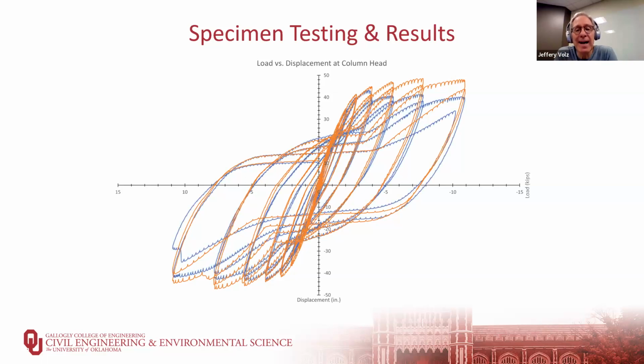And then here's an overlay of the SCC, which is this plot, for those of us who are colorblind, this blue plot. And then this orange plot is the UHPC, and you can see the difference in behavior. So again, the SCC started to decrease in capacity a little quicker. Earlier on in the cycles, the UHPC was still picking up peak load and decreased just a little bit before the very last cycle. So it's going to absorb more energy.